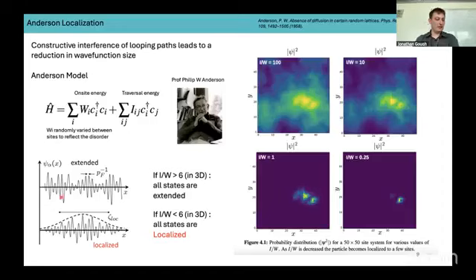So it basically converts your extended states, like a Bloch wave in a periodic crystal, to this localized state where it has this localized envelope over the top of it, given by this localization length. So people often forget as well with Anderson localization, it's not just the wave function that shrinks. The other main result was there exists this ratio between I to W, in 3D anyway, where all states are extended and all states are localized. So this separation between these two regimes is called a mobility edge.